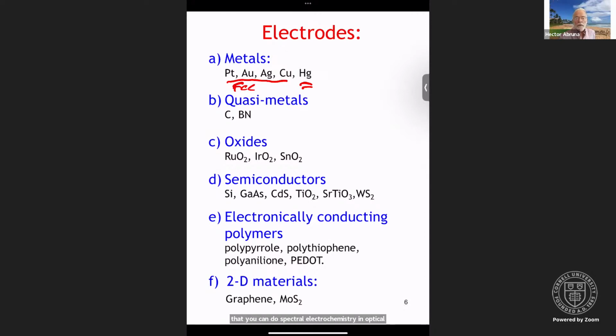studies. Semiconductors, there's a very broad range of semiconductors. The prototypical one being silicon in all of its forms, and then a bit more sophisticated, gallium arsenide, cadmium sulfide, TiO2, strontium titanate, tungsten disulfide, tungsten diselenide, etc. These are transition metal chalcogenides. All of these things have been studied in great detail, and in particular because of the relation to photoelectrochemical or solar energy conversion, and also part of those, the perovskites that have been sort of the latest in those developments, with very high conversion efficiencies exceeding 20%, which is really astounding.